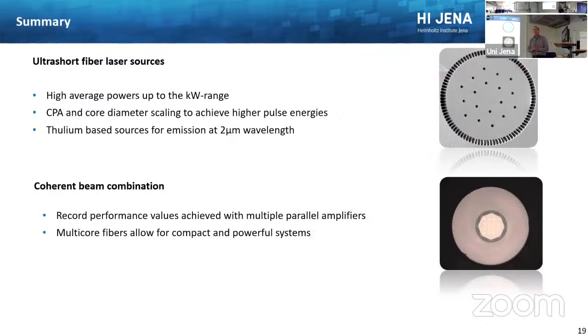So what I've shown you is that ytterbium-based fiber laser systems emitting ultra-short pulses can now provide, let's say, up to a kilowatt average power with this kind of CPA and core diameter scaling, with such microstructured fibers. You can go to higher pulse energies, up to multiple hundred microjoules. We have opened up new possibilities in application with thulium-based sources, also incorporating these advanced fiber structures at 2 micron.